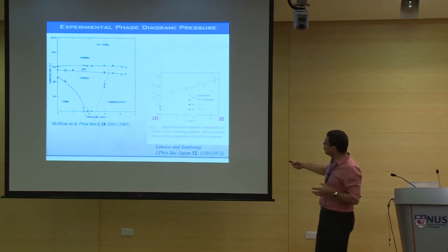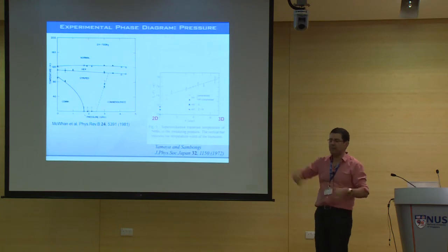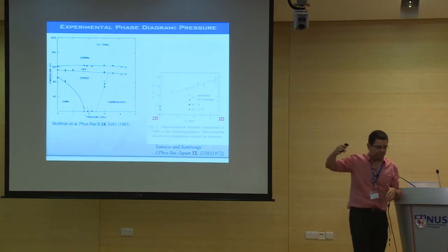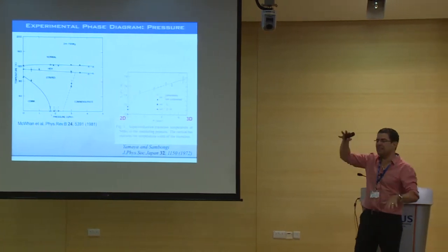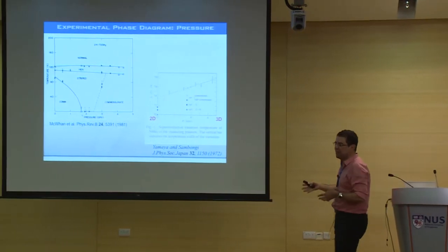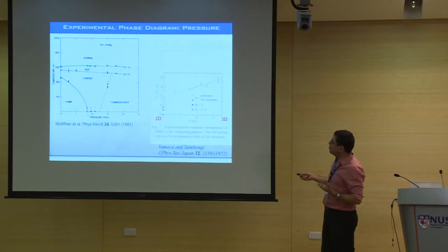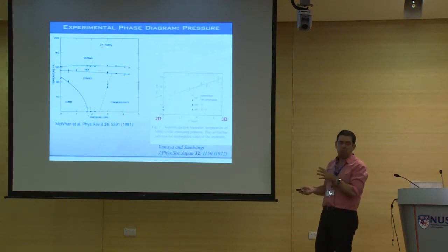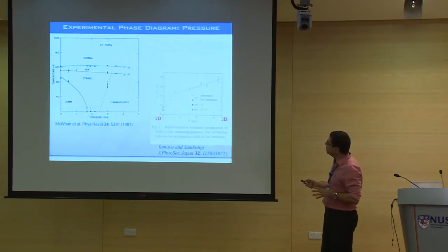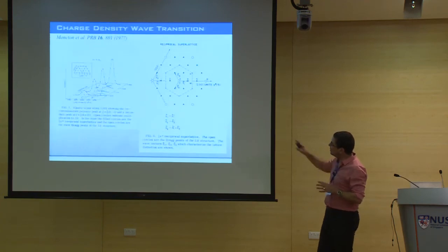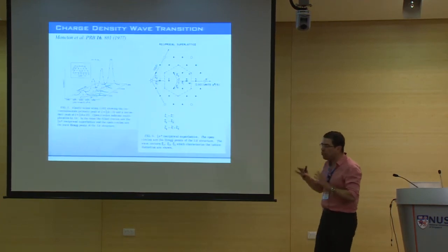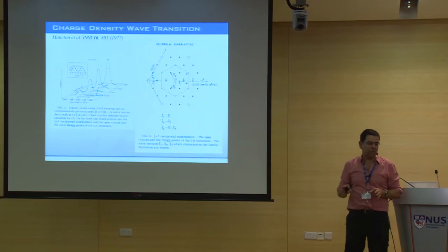And then you look at the superconductivity and you apply pressure, and as you expect, Tc goes up. Okay? As you compress these layers towards each other, superconductivity stabilizes. Okay? This was done long ago. Not many people know about this data, but I find this quite interesting. And actually, this is the charge density wave. It was fully characterized by neutron scattering.